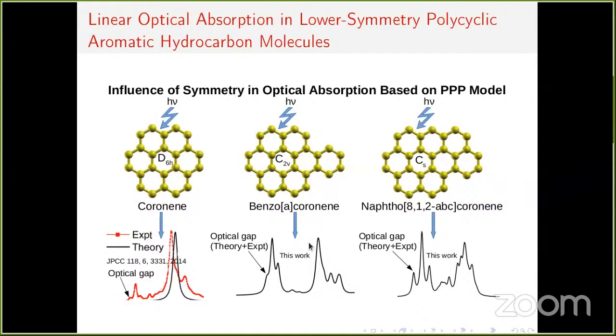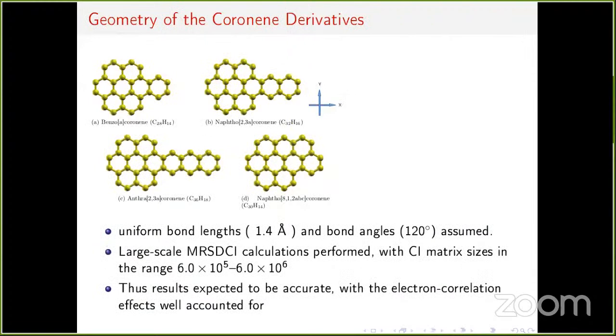The net of our results, the comparison, is shown here. One can see that the optical absorption spectrum changes significantly when the symmetry is lowered from D6h to C2v to Cs, as the molecule becomes less and less symmetric. But we'll go deeper into the subject. In this particular paper published last year in JPCC, Journal of Physical Chemistry C, we in reality studied four molecules. The first one and the last one I showed in the previous page. So you add one more phenyl ring to the coronene and you get benzocoronene.